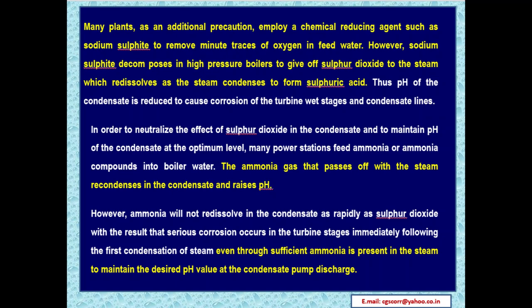In order to neutralize the effect of sulfur dioxide in the condensate and to maintain pH of the condensate at the optimum level, many power stations feed ammonia or ammonia compounds in boiler water. The ammonia gas that passes off with steam recondenses in the condensate and raises pH. However, ammonia will not redissolve in the condensate as rapidly as sulfur dioxide, with the result that serious corrosion occurs in the turbine stages immediately following the first condensation of steam, even though sufficient ammonia is present in the steam to maintain the desired pH value at the condensate pump discharge.